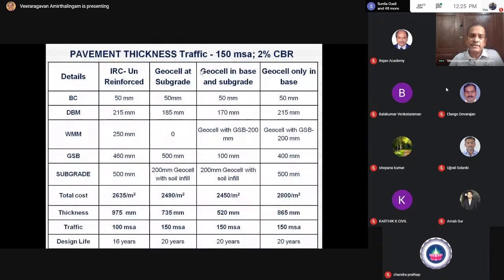What are the advantages? I can use the IRC conventional design, thickness required is 975. I use a geocell only as a subgrade, thickness reduction is possible to 735. Use a geocell in the base, I can reduce thickness to 520. Only the base course 865. So from 975, I can bring the thickness to 520 by using a geocell. So this lasts for 16 years, this lasts for 20 years. If this costs 2,635, this will cost 2,450.